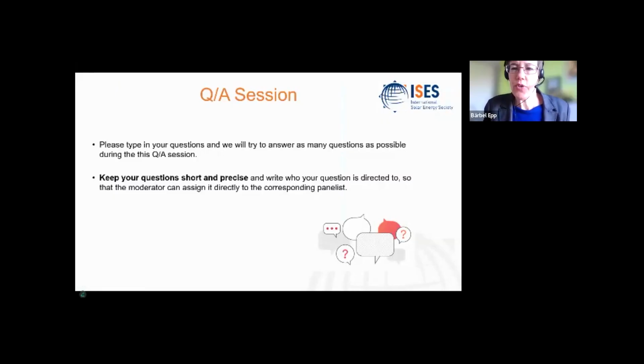Okay. Danielle, you were also asked, the question is relating to heating rate, how to choose the heating rate for different PCMs. So I think the question is focusing on characterization. So when you measure, for example, calorimetry with DSC, so you use a DSC for measuring phase change materials, it strongly depends on what you want to see. If you want to measure temperature accurately, you will choose low heating rates, because then the thermal transport processes can be neglected in the sample. If you want to evaluate the specific heat capacity of a solid or a liquid phase, you need to use higher heating rates because of the sensitivity of the system. The higher the heating rate gets, the higher the sensitivity gets, and the more accurate the results get. So it's, again, strongly dependent on what you want to measure.